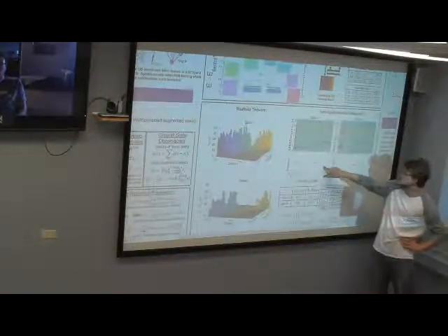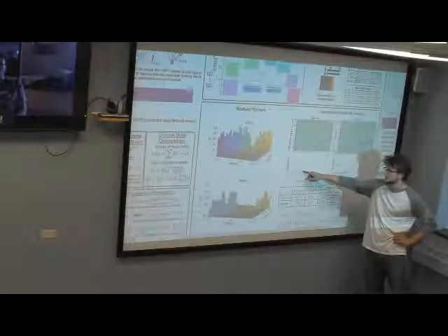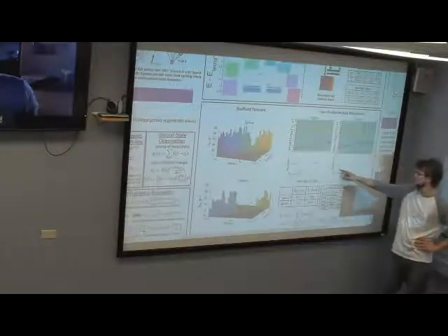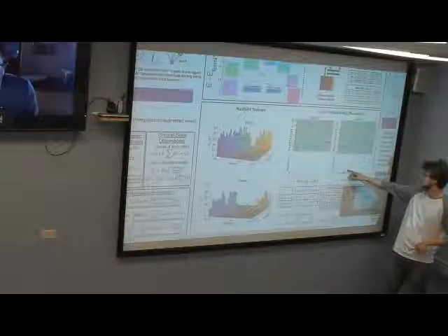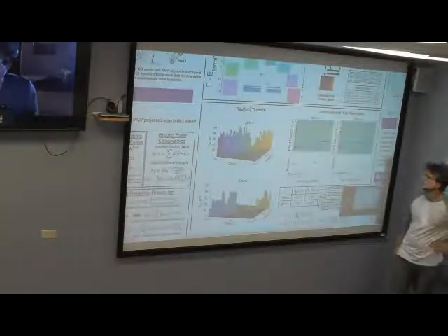These plots just show how the population relaxes in time. You can see it's a very quick relaxation from pretty much each state all the way to the HOMO. Whereas here there's a bottleneck that happens from around HOMO minus 2, HOMO minus 1, then up to HOMO.